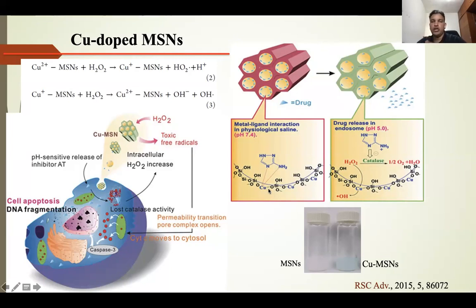So the usage of loading copper inside the framework is first to create free radicals, through this mechanism, toxic free radicals which can kill cancer cells. And the second thing is loading the drugs which can specifically release in the acidic environment, that is cancer or bacterial infections as well, because all acidic environments can degrade the linkage between the drug molecule and the metal, because these coordinations are pretty sensitive only in the acidic environment. So when you administer these through blood, blood pH is around 7.35 to 7.4. So these are safe. These interactions may not be disassembled. So the drugs are safely taken to the acidic environment, especially cancer and bacterial infections.